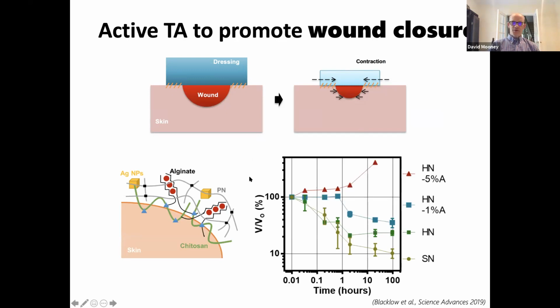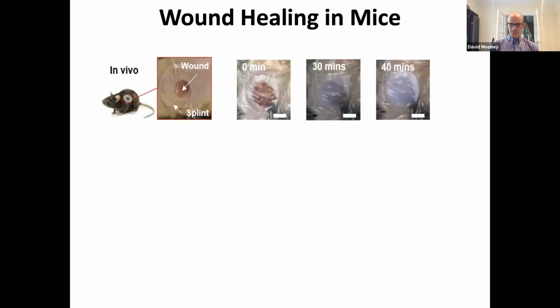And so this just shows the normalized volume of some of these gels as a function of time after being placed at body temperature. Depending on the composition, and particularly when he incorporated PNIPAM, he could get an appropriate phase transition that would lead to significant contraction.